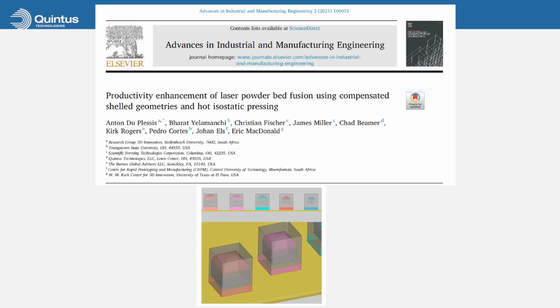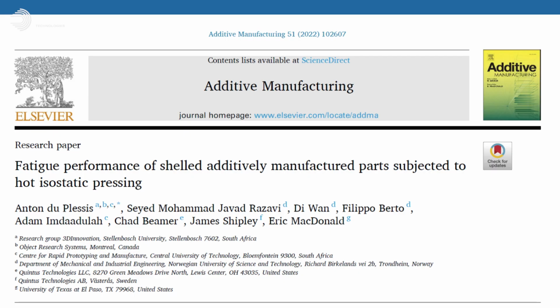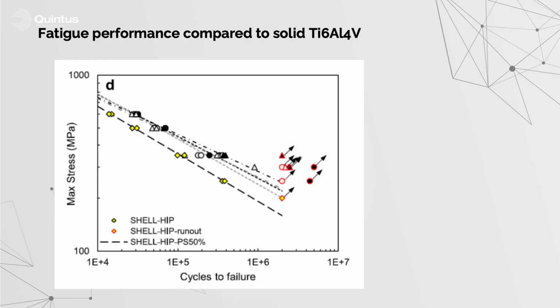In the most recent paper that was just published this year, we studied, in a similar process, solid laser powder bed fusion material with rough surfaces compared to the rough surface HIPed and shelled components. In this case, the fatigue strength and the lifetime were reduced slightly, about 20 to 25%, or maybe 30% in some cases. But this is still surprisingly good and much better than without HIPping. Compared to the as-built state, it's still a significant improvement.